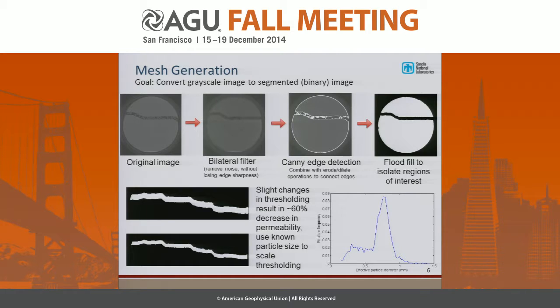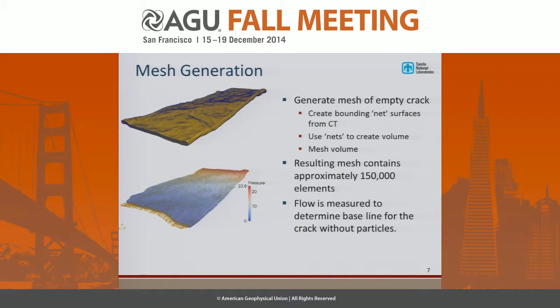It's pretty tough to threshold and determine exactly what size the fracture is from the CT data. So what we do is use the known particle size — because it's a sieved sand — to optimize the thresholding level so we can arrive at an appropriate fracture size. We then mesh the fracture itself, which is reasonably computationally expensive. We've got 150,000 elements, just trying to maintain three to four elements across the crack volume. We then perform flow simulations on this to establish a baseline for the empty crack.